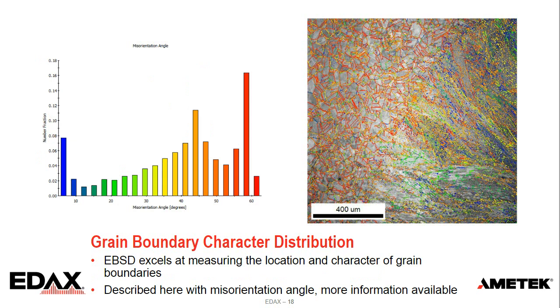One of the things EBSD really excels at measuring are grain boundaries, and what I've called here the location and character of grain boundaries. And what that means is we can tell what the misorientation between two pixels is. You know, we measure that angle. We use that when we created the grain tolerance angle. So if it's a misorientation that's between, say, 20 and 25 degrees, we can color it one value. If it's between 40 and 50 degrees, we can color it another value. And so we can measure lots of grain boundaries with EBSD. It's really the most efficient tool for looking at this orientation information because we can look at a large area with fine spatial resolution.